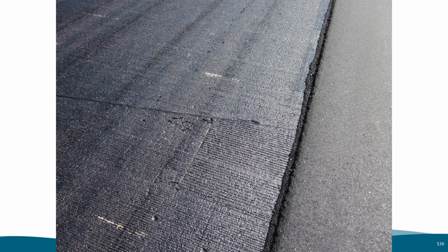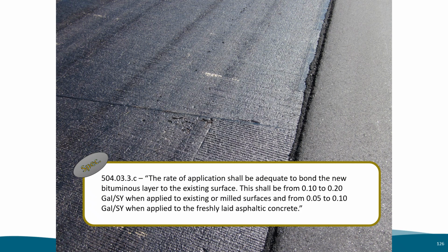This image of tack over Portland concrete pavement is showing tine marks and grooves. Trucks and traffic can pull out small fines, often leaving not enough tack coverage. The contractor's tack truck needs to apply a heavier application of tack to these surfaces. As written in the standard specification, the rate of application shall be adequate to bond the new bituminous layer to the existing surface. This shall be from 0.10 to 0.20 gallons per square yard when applied to existing or milled surfaces, and from 0.05 to 0.10 gallons per square yard when applied to freshly laid asphaltic concrete.